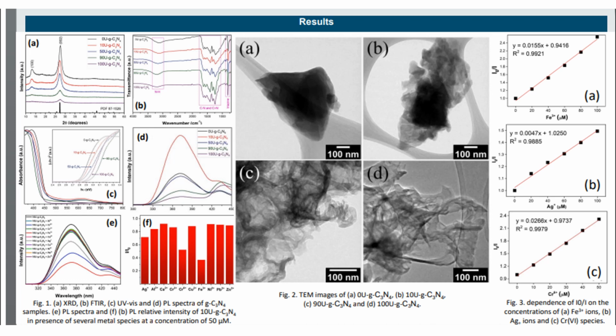The linear relationship between the fluorescence intensity of the 10% urea graphitic carbon nitride sample excited at a wavelength of 250 nanometers and the concentration of iron 3 ions in a range of 0 to 100 micromolar shows a correlation coefficient R² estimated at 0.9921, and the limit of detection was calculated at 7.2 micromolar. The sensing of silver ions in a range of 0 to 100 micromolar shows a linear correlation coefficient R² of 0.9885 and a limit of detection of 8.4 micromolar. The linear regression between the chromium 6 concentration and the I0 to I ratio in a range of 0 to 100 micromolar yielded an R² coefficient of 0.9979 and a limit of detection of 1.9 micromolar.